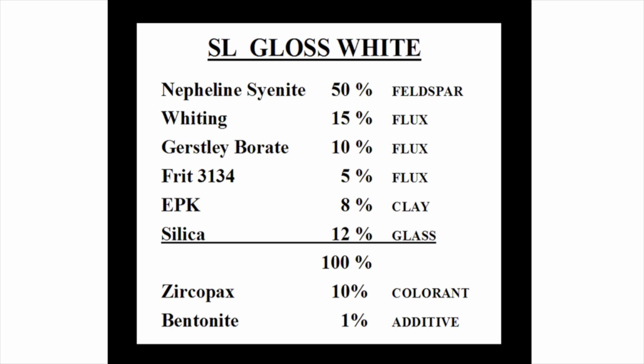Let me divide glazes into two categories, matte and gloss glazes. First, the feldspar content will almost always be the highest amount of any ingredient in the glaze, therefore it is the bulk ingredient and component part of the glaze. Matte glazes generally have a high clay content, whereas glossy glazes have a relatively high silica content.